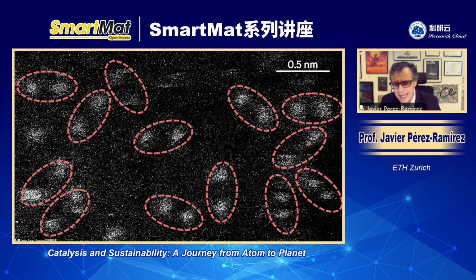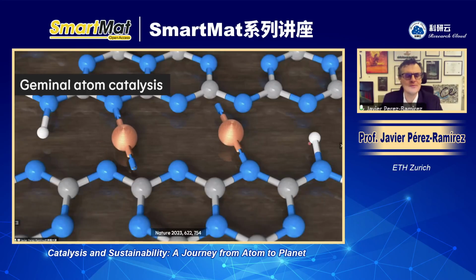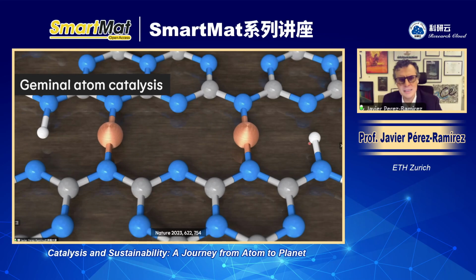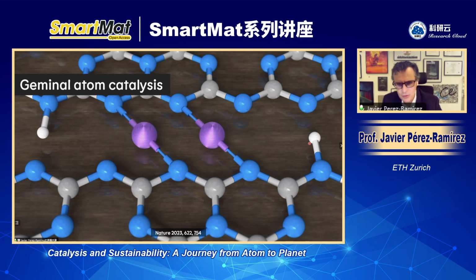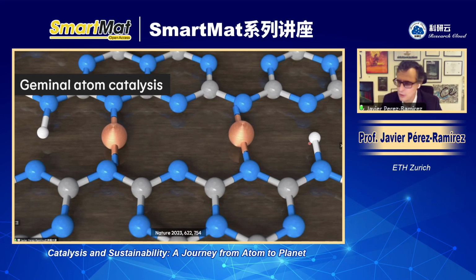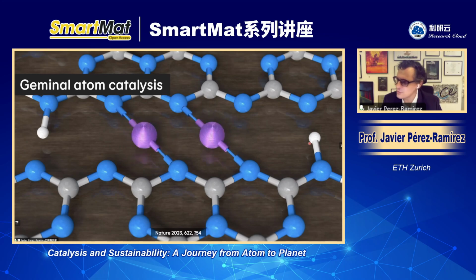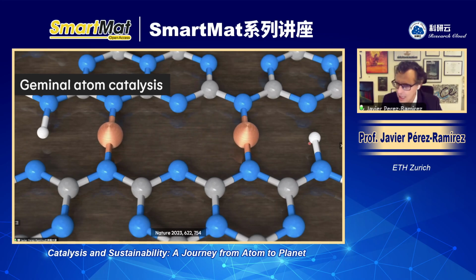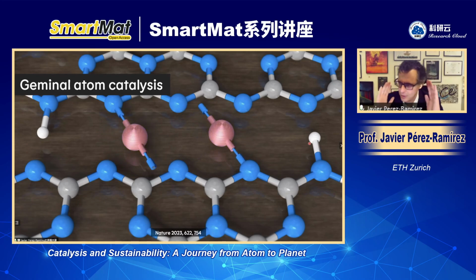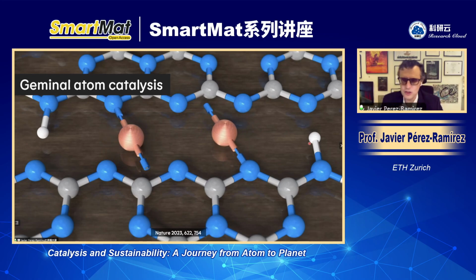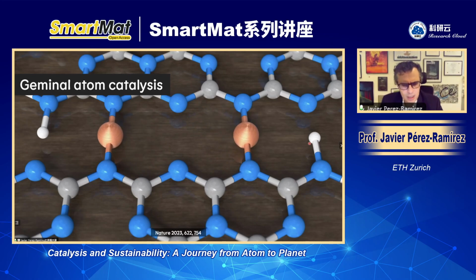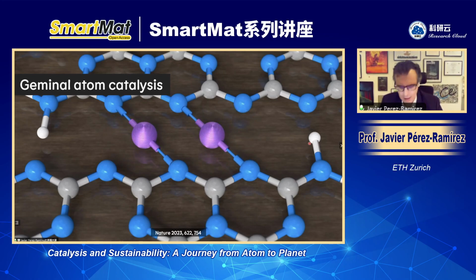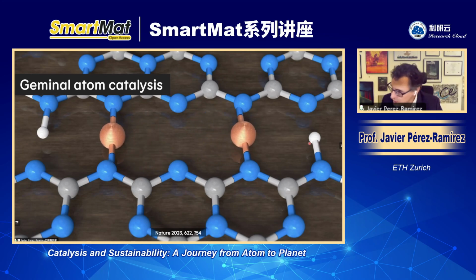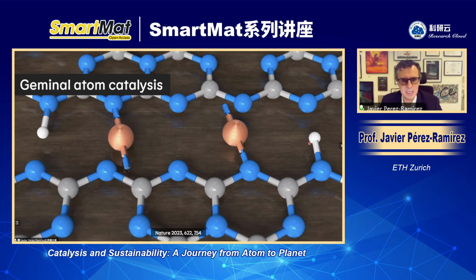And they generate unique reactivity because they are quite dynamic. It's not only that they are close, but they're also quite dynamic. So what I'm going to show you is exactly how dynamic they are. That means that they can shuttle from one nitrogen to the other and get closer than 4.07 angstroms, that's the ground state distance, when you are doing chemical reactions. The driving force of chemical reactions actually makes this transformation from being 4.07 to being closer together. And these findings were published in Nature last year. And I would like to show you what kind of reactions we did to visualize, or to witness this dynamic nature.